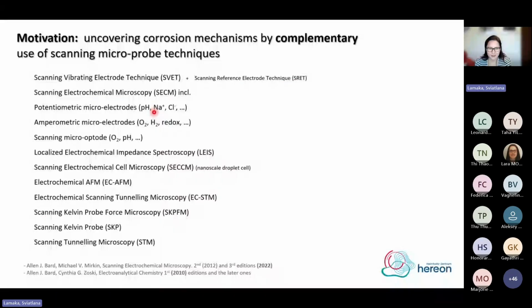So before we start talking about the techniques themselves, let's try to understand what exactly we are trying to catch with these local electrochemical methods. Anodic oxidation and cathodic reduction processes lead to significant changes at the metal interface. We have strong ionic fluxes generated due to anodic oxidation, then hydrogen evolution due to the reduction process, and oxygen reduction, which is the main cathodic process for aluminum, zinc, and iron-based alloys, and a secondary process for magnesium. This also leads to evolution of gaseous hydrogen, consumption of oxygen, and local alkalinization as a result of these two cathodic processes.